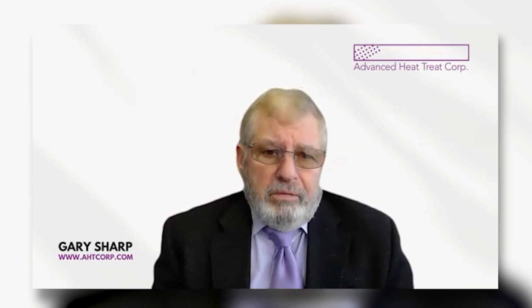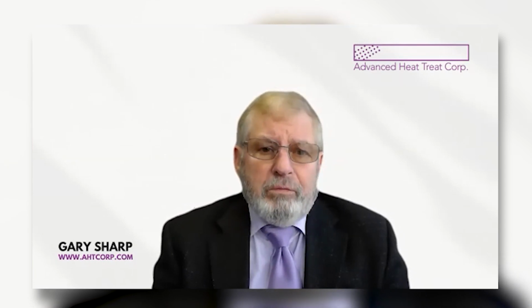And like you mentioned, there's ion nitriding, there's gas nitriding, there's salt bath nitriding. All three do similar things. They just have different requirements, obviously, for the material, the chemistry that it's involved with each of those materials. But you can nitride most anything, at least putting a compound zone or an outer layer on that's very abrasion resistant. Where the process gets developed is when you have alloy, chrome, moly, vanadium, aluminum.